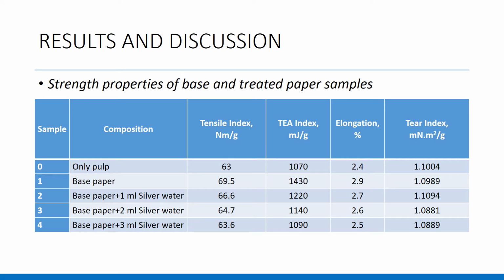The main purpose of silver water treatment is to achieve antibacterial activity in order to obtain a special type of paper with application in packaging production in important sectors such as household, food packaging, medical and pharmaceutical products. As the consumption of silver water increases from 1 to 3 milliliters, the values of the strength indicators, although within the error of the analysis, decrease. This effect is due to the irreversible destruction of the already formed hydrogen bonds between the cellulose fibers in the paper base, and the subsequent drying after spraying with silver water cannot compensate for the loss of the initially formed hydrogen bonds.